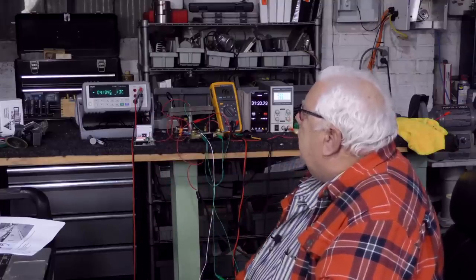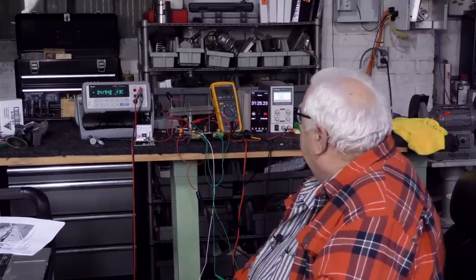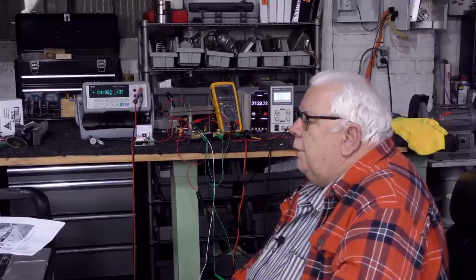Now, I like this now. We're slowly coming up on 4.2, but we're at 31 minutes now. So we started at over 2 C, 10 amps times 46 is 460 amps. Times 345 volts is 158 kilowatts. So we've just demonstrated a Tesla Model 3 cell under the duress of supercharging, not at 125 kilowatts, it's available, but at 158.7 kilowatts. And what is Elon talking about for V3? I think you'll find it's about 160 kilowatts.